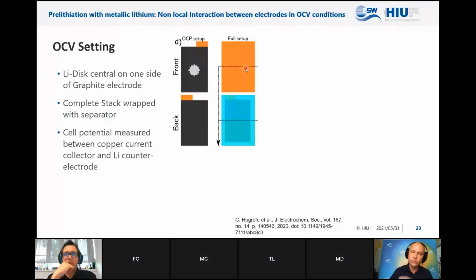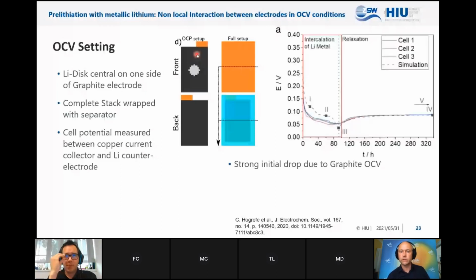The lithium is diffusing through the electrolyte and is intercalating into the graphite electrode, which you see here in the potential signal. So this is no external current, just this lithium on top of graphite. And you see the stages of graphite. So this is the part where the disk is dissolved. Then you have a relaxation regime where you reshuffle the lithium in the electrolyte and you deposit somewhere else. And then you are in an equilibrium situation.